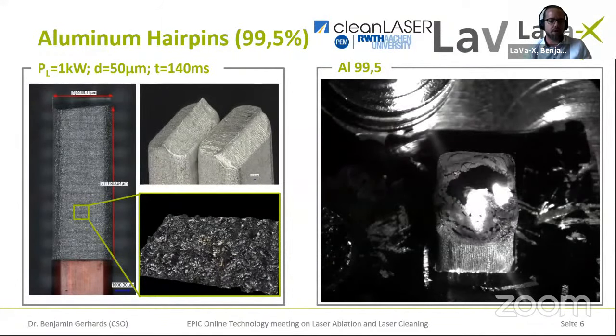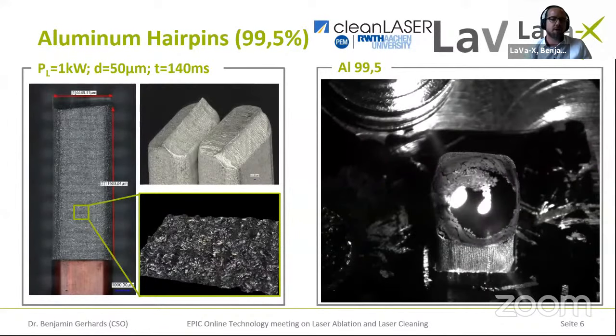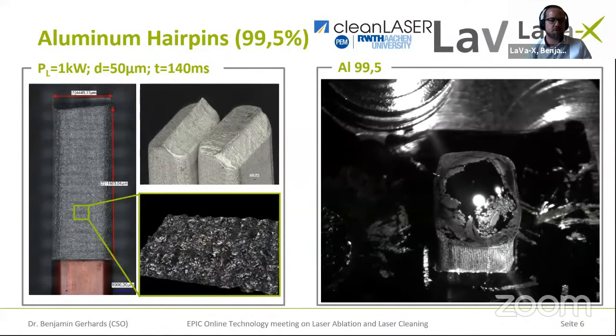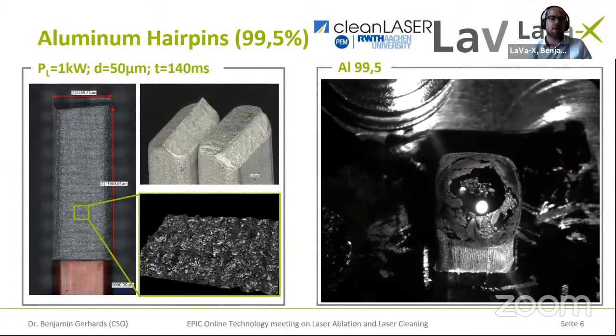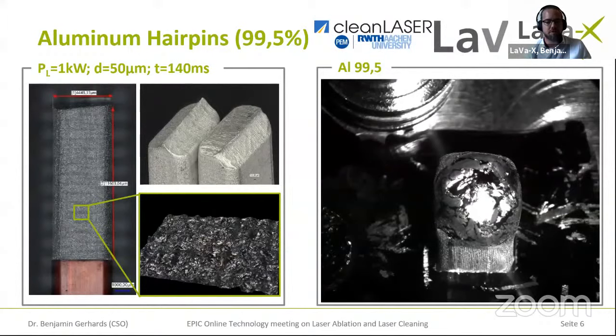And also, what I mentioned earlier, the molten pool stays liquid a quite significant amount of time. You can see the formation of the oxide layer quite swiftly here because we had the lighting for the high-speed images transferred into the vacuum, and therefore had a small leakage. And yeah, now you can see it. But it's still liquid, and you can see now the pores gassing out of the molten pool. And this is quite a huge advantage of our process.